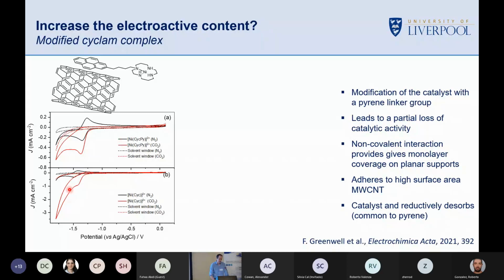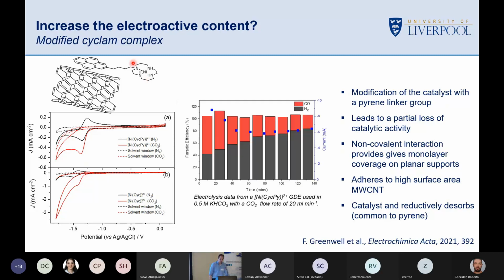So here's the parent catalyst at the bottom. Really big current enhancement under CO2. You put the pyrene on, the current enhancement decreases. Note the scale. It's about 10 times lower. And we know that that happens. That's pretty normal when you modify a cyclam. You muck up its structural flexibility, and you also take away one of the key amine groups which are involved in the catalytic cycle. But we do get very high surface coverages for this catalyst, and we can put that in a gas diffusion electrolyzer.